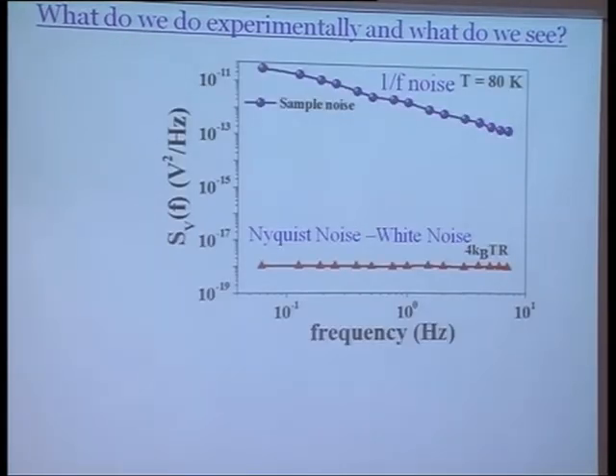Okay. Now, what do we do experimentally and what do we see? What we do is that we have a little unique setup. Phonon temperature is what you measure. This is the bath. So you are connected to a copper block. So any temperature when you measure by putting it to a copper block, this is your phonon temperature.